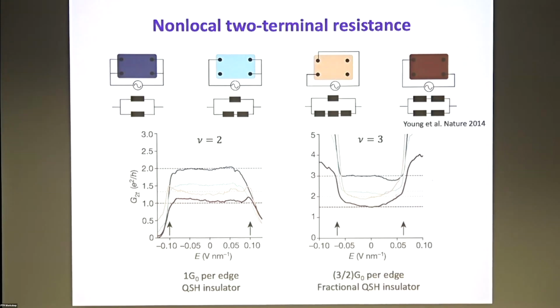You can do the same thing for filling factor 3. At zero electric field, again, you just need to look at the small electric field region. The dashed lines are the expected values, the solid lines are the measured values, and they agree reasonably well. The conclusion is that each edge carries a 3/2 conductance quantum, just like what I told you about. The only state we can think of with quantized two-terminal resistance and zero Hall resistance is a quantum spin Hall insulator. This measurement also really supports that they are helical edge states.